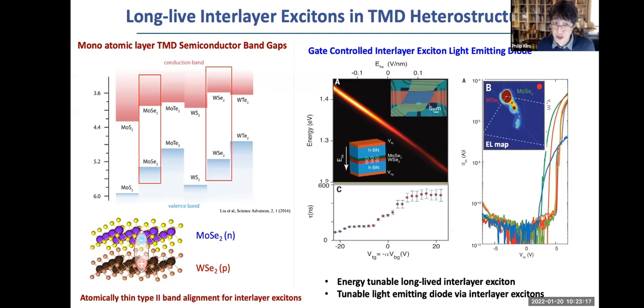So in some sense, you can generate this interlayer exciton by electrical means. Also, you can interrogate the properties of the interlayer exciton by observing the light emission from the devices. And quite recently, there have been further exciting demonstrations. In the previous device I just showed, it's a PN junction. Although their lifetime is long, something like a few hundred nanoseconds, it is not infinite yet.